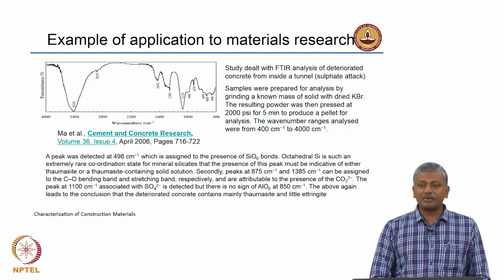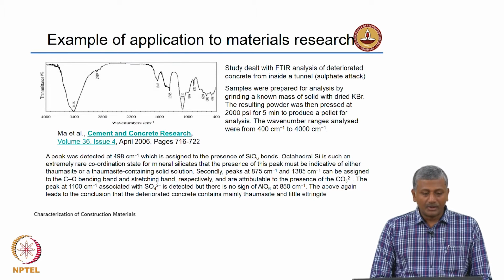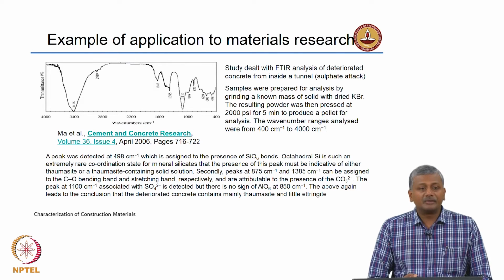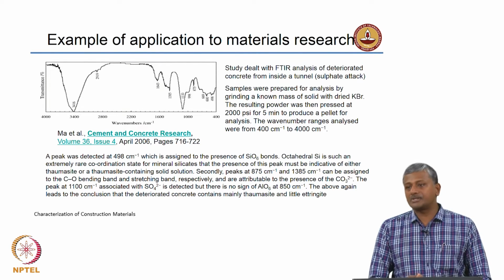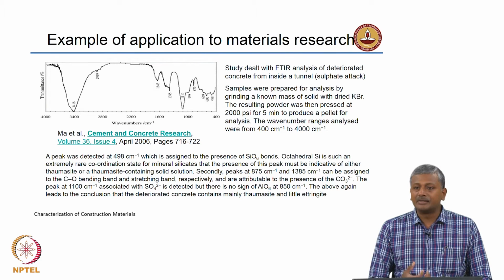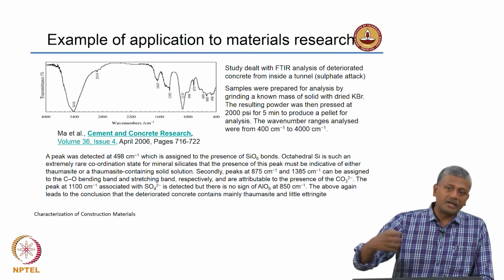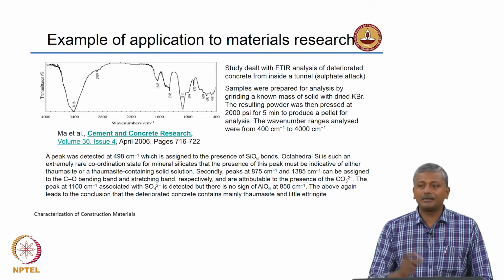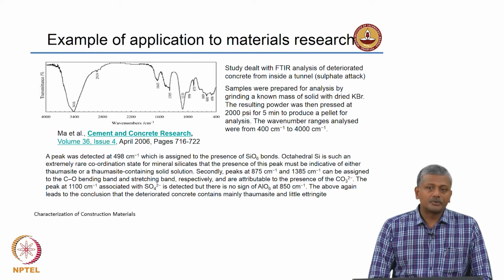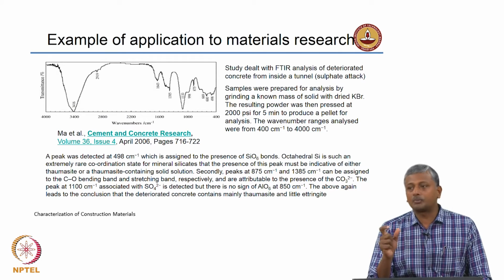So, just to give you an example of application of FTIR to materials research. Here there was an investigation of concrete that was taken from inside a tunnel. This tunnel was in a mountainous region which had a soil rich in sulphate, and a lot of the sulphate was penetrating into the concrete and creating a lot of damage at the surface of the concrete. So, the investigators wanted to analyze what kind of products were actually forming in the system.